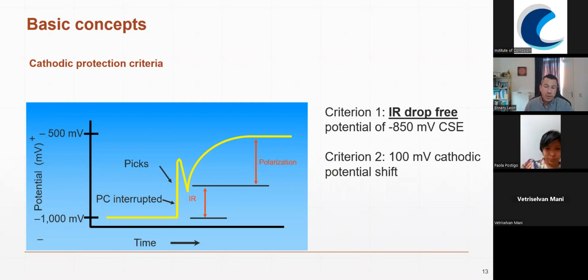This criterion is based on the fact that we can eliminate the IR drop from the equation, and this can be done by switching off the TR, or disconnecting the galvanic anodes, or placing the electrode close to the structure. Okay, and it's important to bear in mind that once we switch off the TR or we disconnect the anodes, we will have a peak in the potential reading. It will become more electronegative, then more electropositive, and eventually depolarization will start taking place. So we have to know when we want to take the reading, and usually it's less than 1 second after we switch the TR. We need to take the reading.